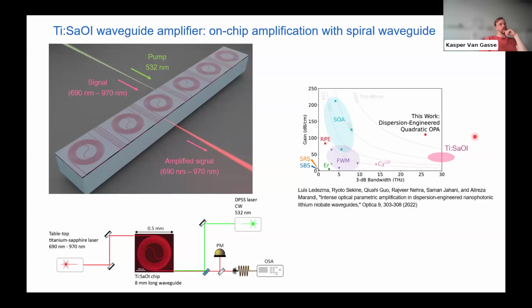But then if you look at the titanium sapphire, you can see that the gain bandwidth of the TiSaph is really completely out there. It's much wider than any of these traditional systems, and even outperforms this very advanced optical parametric amplifier. And the gain is also quite high per unit length, still higher than erbium. However, still not on the level of a Ti:SaOI, which would be very hard to compare to. But you can see that we trust that it is a very promising system for future on-chip laser technologies.